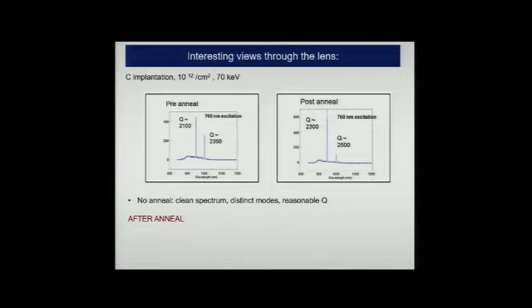That means the photon loss is slightly less. That means maybe we have removed some defects. But the fact is that the ratios are different. That means if the ratios are different, that means there are more photons emitted into that self-same mode. What we've done is just do an anneal, and I'll show you what it actually looks like in the next slide.